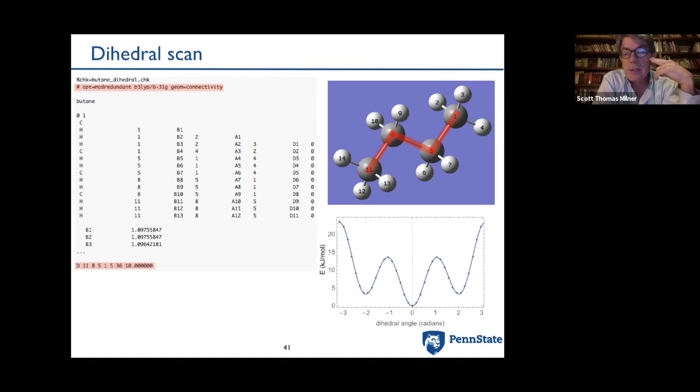Getting angle potentials is a little bit tricky sometimes because the angles are coupled together. So if you imagine taking methane, here's a carbon and tetrahedral hydrogens. If you open one of the HCH angles a little bit, you can't do it without changing other ones, just because of the geometry of the molecule. So if you've got all the HCH angles in your potential and you open one of them, then some of the other ones get opened as a side effect as you scan that. You have to take account of that when you're fitting the spring constant of that angle. But that can be done.